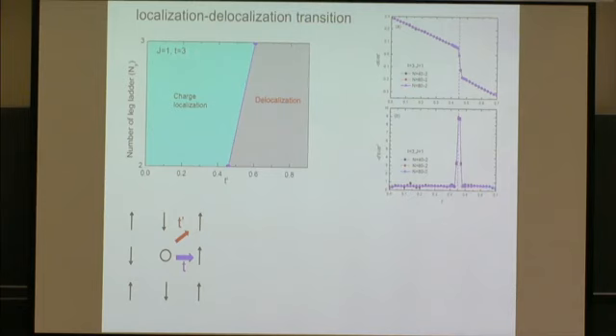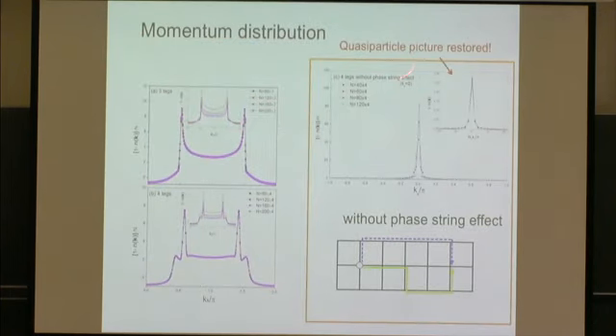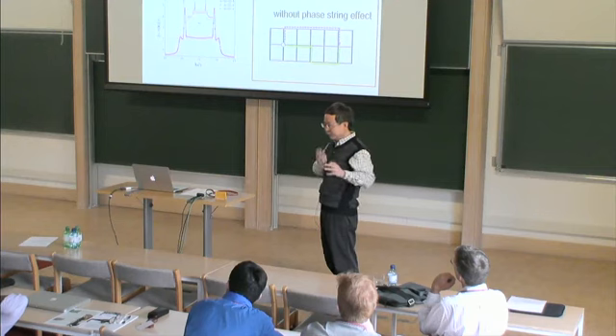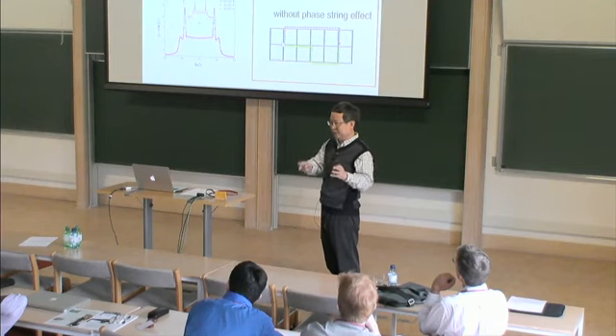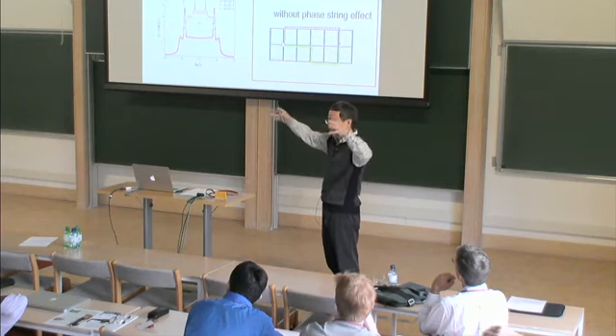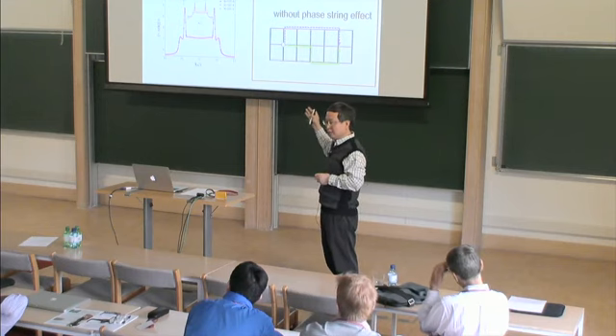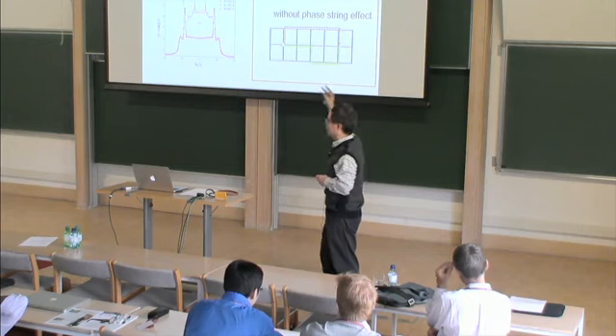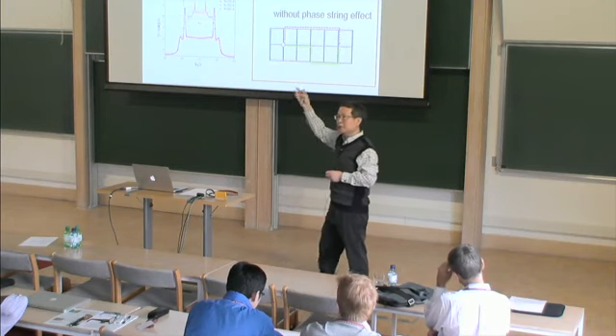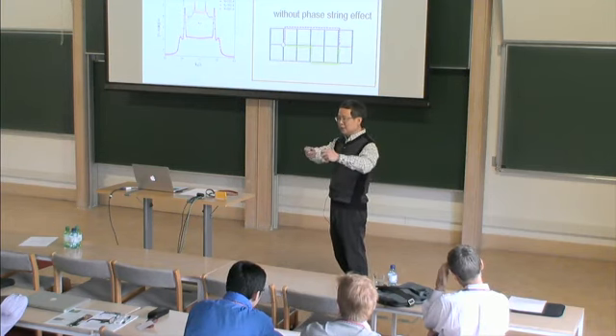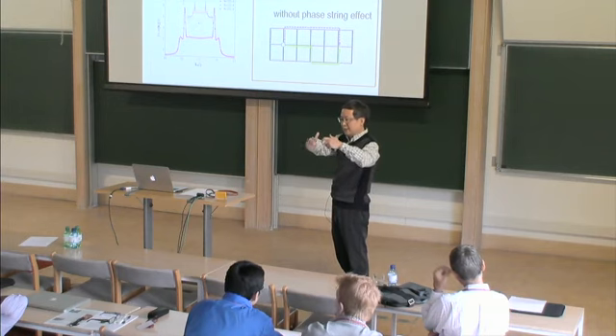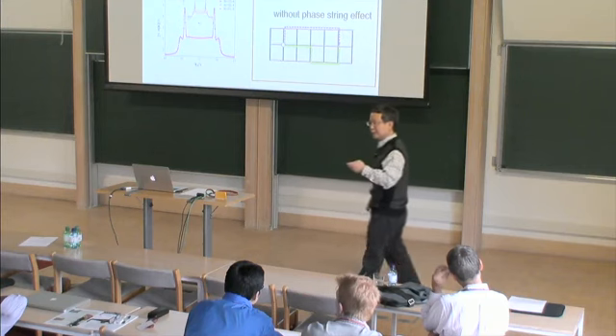What's the value of J in the previous figure? I actually mentioned that all these calculations use t over J equals 3. We checked over all values. At very small t, there's a phase separation or something. But generally, this will hold, until t is like 30 J, and then you have some polaron coming out. That's also a polaron.